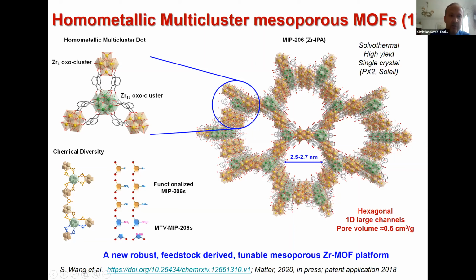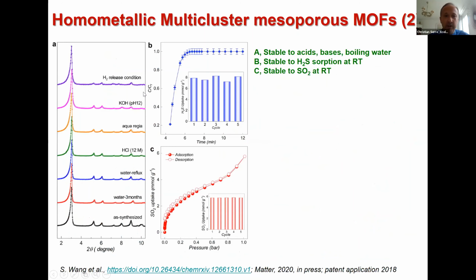And then the ligand also is very interesting. It is very cheap isophthalic acid that is commercially available, derived from feedstock. And then you can use many different functionalities in this material to make functionalized material, and then also multivariate material. So it is really an interesting mesoporous zirconium platform.